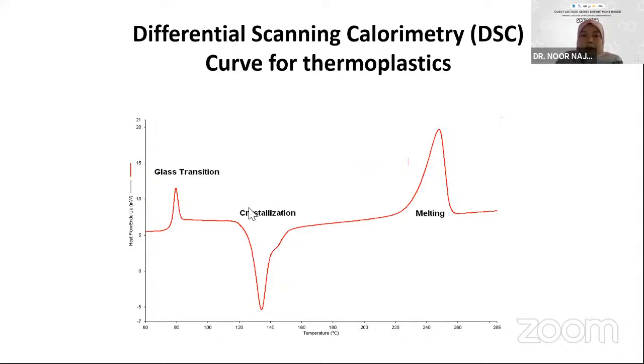So sometimes the DSC can give you the glass transition temperature, but for certain samples, I have experienced that I cannot get the glass transition temperature from the DSC, but I can get it from dynamic mechanical analysis, because dynamic mechanical analysis provides you the information of tan delta. The tan delta in the dynamic mechanical analysis represents the glass transition temperature of your sample. So if you have this kind of peak earlier in the curve, meaning at an earlier temperature of your process, it represents glass transition temperature. If you don't have this kind of curve and you only have this kind of curve, this one represents your melting temperature, not glass transition temperature. Okay, does that help you, Vira? Yes, very much. Thank you.